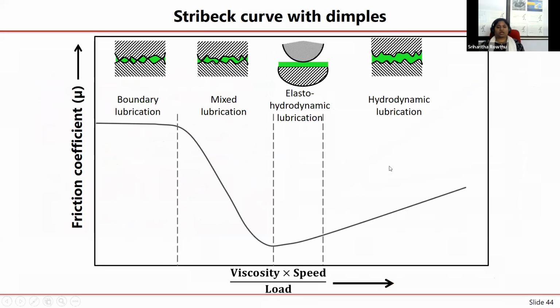Okay, so the last part, which is something I personally like, is that we know this is our Stribeck curve, right? Stribeck curve is basically plotting your friction coefficient against the Hersey number. Hersey number is this particular thing, viscosity times speed divided by load, that is your normal load. So you have several regions: boundary lubrication, mixed, hydrodynamic, and for this ball and flat, also elastohydrodynamic. Obviously you would like your friction coefficient to be as small as possible for most of your applications. So it's important to generate your Stribeck curve.